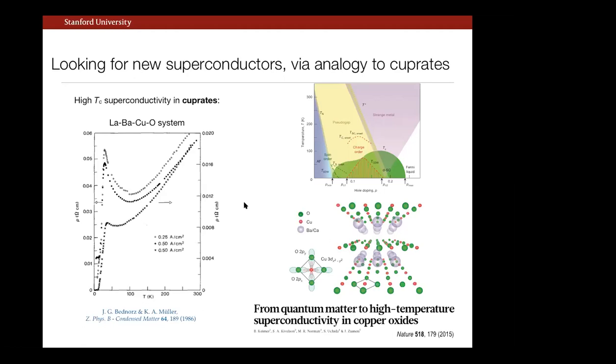One is, it's actually quite a complicated phase diagram, but simply speaking, the cuprate superconductors all arise from a parent compound, which is an antiferromagnetic insulator, a so-called Mott insulator, in the sense that the insulating gap comes from strong electronic correlations. And as you either hole dope, as shown here, or electron dope the system, you encounter a dome of superconductivity. Now, there are quite a few other instabilities and important features that I'll neglect in this discussion, but this statement is quite general, that we're always doping out of this antiferromagnetic insulator.